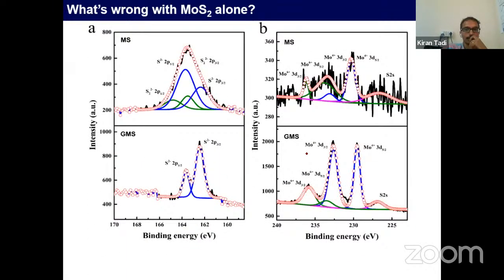We also performed this on molybdenum sulfide without protection of graphene. So it is converting to Mo6+ and Mo4+, it is oxidizing. For the GMS, you can't find that much high areas of this Mo6+. Maybe during the transfers there are small peaks you might get, but you don't find how much Mo6+ is etched or oxidized. That much you didn't find in this graphene-protected molybdenum sulfide.